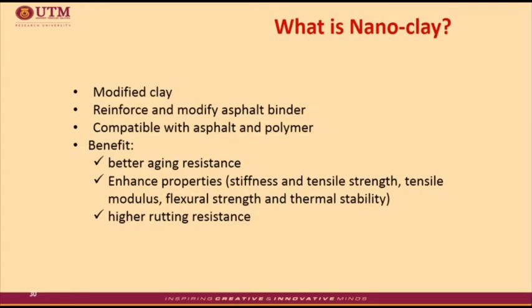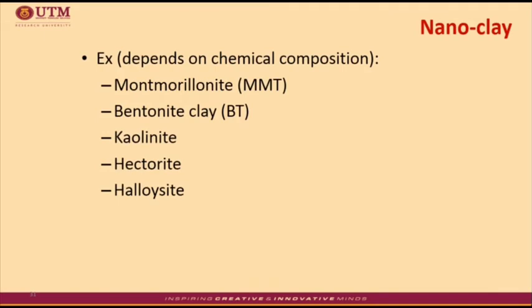For example, in some research work, it was found that 2% of nano clay in the asphalt binder may increase the shear complex modulus to almost 2 times that of the conventional asphalt binder. This indicates a massive improvement in the rutting resistance of asphalt. Otherwise, nano clay is also used to improve the modulus and tensile strength, flame resistance, and structural properties. Nano clay is widely used in modification of polymer to improve the mechanical and thermal properties.